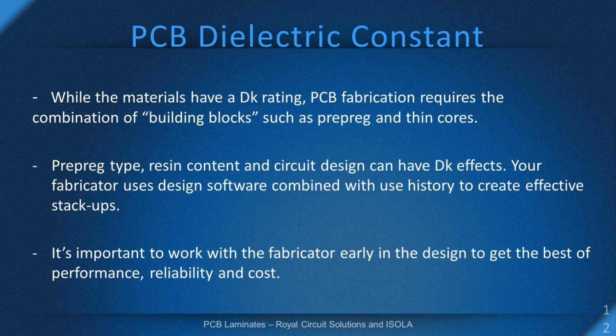So when we go to create a stack up for impedance values, we have different building blocks that we use. We have the pre-preg and the cores. We also take into consideration the trace sizes, the spacing for differential pairs, and also reference planes for modeling the impedance. We have software that we use to model this impedance. We do a lot of this for designers at pre-layout stage so that they know exactly what traces to route to accomplish their impedance target values. And also we take into consideration whether they're looking for a low loss or very low loss material.